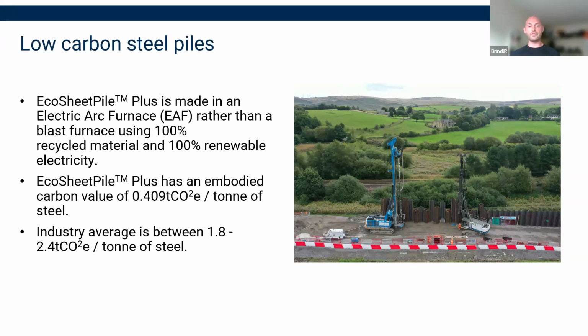So this change in the manufacturing process has significantly reduced the embodied carbon of the piles. With the industry average at anywhere between 1.8 to 2.4 tonnes of CO2 equivalent per tonne of steel, we're looking at a potential 80% reduction in embodied carbon if the Eco Sheet Pile Plus range are procured, as their EPD states a value of under half a tonne of CO2 equivalent per tonne of steel. It's worth also noting that this only relates to the A1 to A3, so that's the manufacturing stage of the steel elements, and therefore transportation needs to be considered and assessed when completing your carbon budgets.